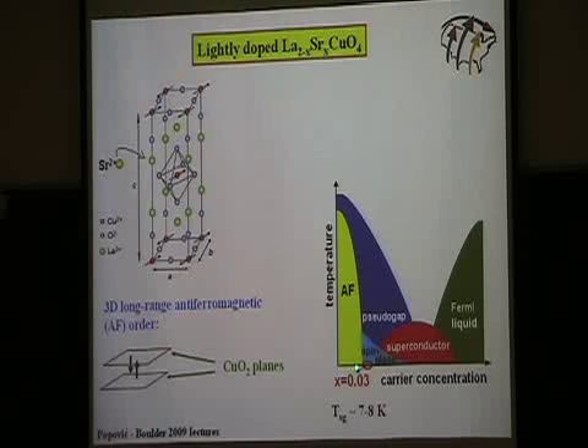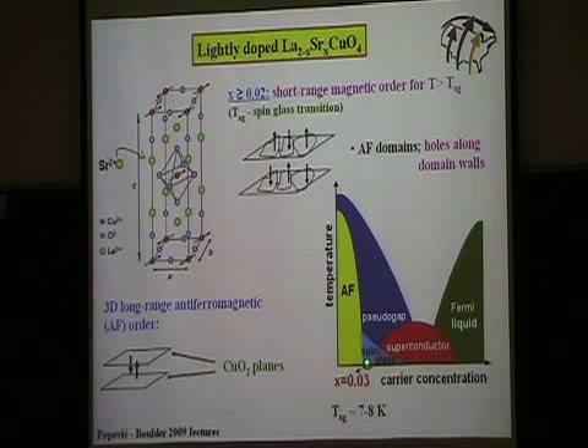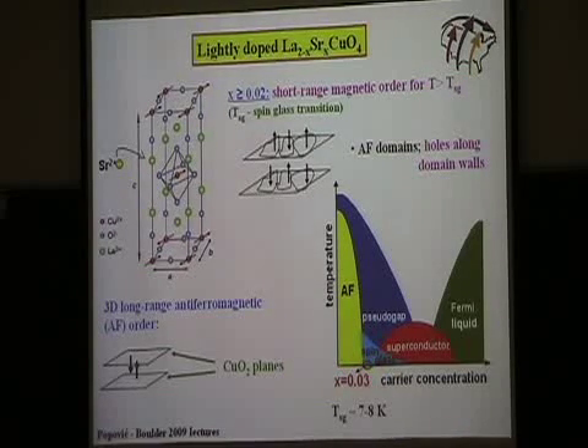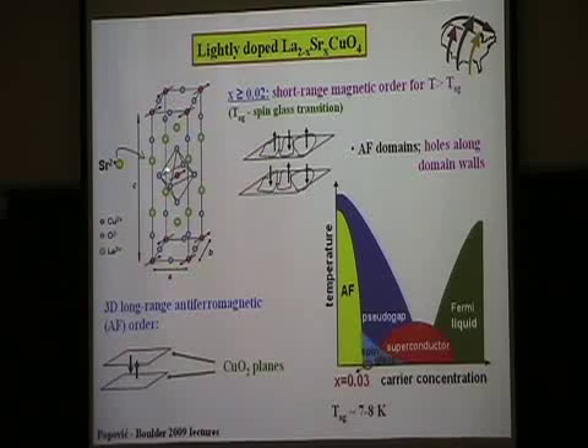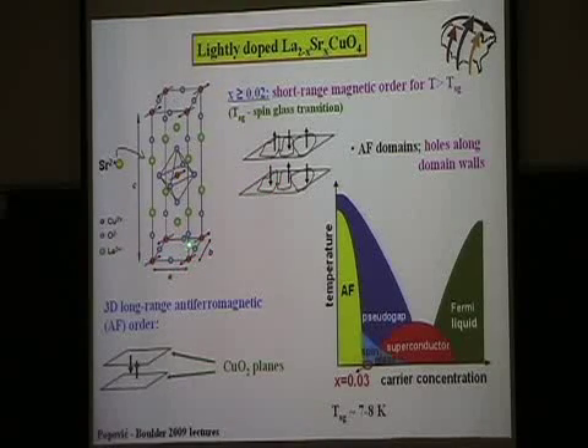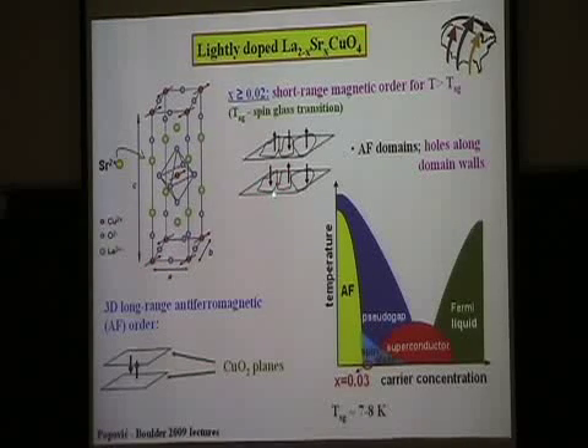Then you put a little bit of doping, like 2%, you kill this long-range order. But even after you kill it, like in this regime, people have determined that short-range antiferromagnetic order persists. So you have domains. Each one has a component of the spin pointing along the z-axis. And there are many experiments that suggest that these doped holes actually live along these domain walls. So this is just antiferromagnetic ordering, short range, just like in this undoped material. We put holes and they live in these domain walls.